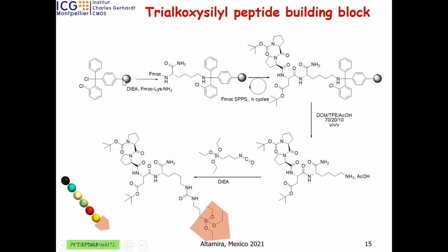It's very easy for them. We can grow the amino acids one by one. It's automatic, you know, we have a robot. You can design your sequence and one by one you can grow it on the solid substrate, the resin here, and you grow your peptide and then you cleave it. Then silylation here, thanks to this NH2, you can immobilize the silica part, or silane part, sorry, and at the end you obtain the silylated peptide. It's very easy, but you have to work carefully.